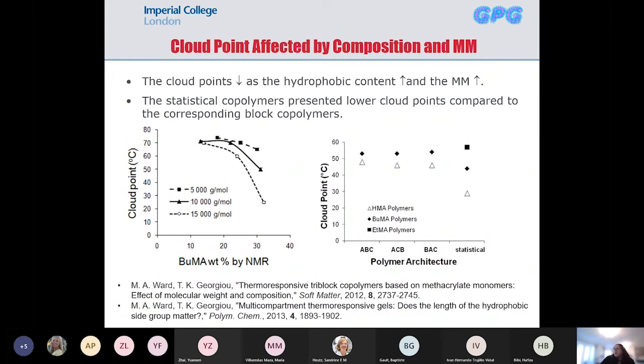Now, in this case, we have two graphs where we investigate the cloud point, so the temperature where the solution becomes cloudy because the polymer is becoming more hydrophobic and precipitating out. So the cloud point versus the content of the hydrophobic monomer, and the cloud point versus the different architectures. In this case, we have also done different molar masses. So as you increase the hydrophobic component, if we look at one curve, the cloud point decreases. This has been observed before in some studies, because you make the overall polymer more hydrophobic, so it will have a lower cloud point. In terms of the molar mass, for this system, we found that as you increase the molar mass, the cloud point also decreases.